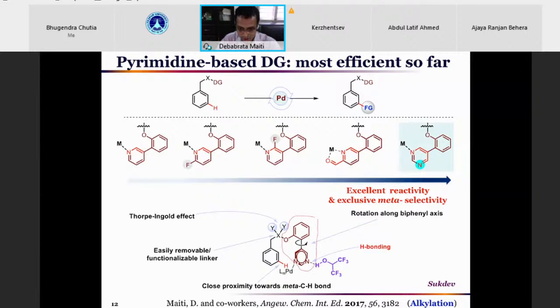What are those? Well, you have 2 nitrogens, so statistically you have a higher probability of finding palladium and placing it in front of the meta CH bond. You have hydrogen bonding with the solvent, hexafluoroisopropanol, which is also assisting in carbon-hydrogen bond activation. You have free rotation, which is also assisting in positioning the metal with respect to the organic substrate. Preferably, you have the Thorpe-Ingold effect, which is bringing the organic substrate and ligand into close vicinity of each other. With this ligand, previously unsuccessful reactions such as alkylation and cyanation can be done. A series of small natural products as well as agrochemicals and pharmaceuticals can be synthesized by utilizing this method.